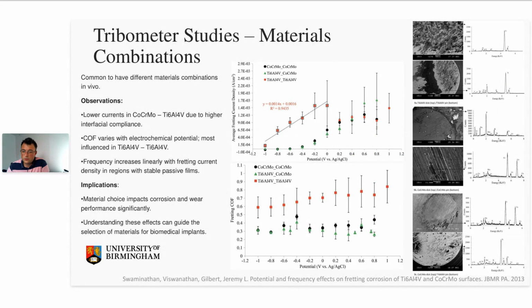But the additional complicating factor here is that the resulting fretting corrosion, the resulting coefficient of friction, and, in later studies, the energy dissipated and wear, are also a function of the applied potential that we test these at. And again, there's a lot of debate around how you choose a voltage or an applied potential to test at, but ultimately what we have is a way of being able to control the reaction kinetics to systematically look at what's occurring at interfaces, and then try to work that backwards to optimize the device interface.